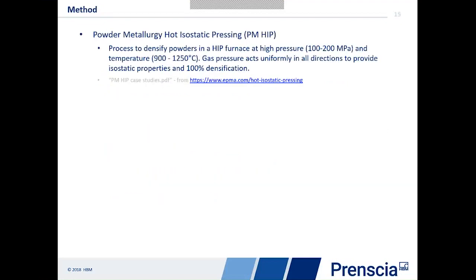So the method we're using here, first of all, when it comes to powder metallurgy, is that a partner of ours has given us components which they've made using powder metallurgy and hot isostatic pressing. This really is an alternative way of doing the type of casting things. We can fill a cast, if you like, with powder metal, and then through hot isostatic pressing, we can actually create a component like the ones that we saw earlier. These go into a furnace. The pressures are typically 100 to 200 megapascals at temperatures between 900 and 1250 degrees C. The idea of this is it provides isostatic 100% densification. It squashes those, heats them together and fuses them together to make a material and a component.